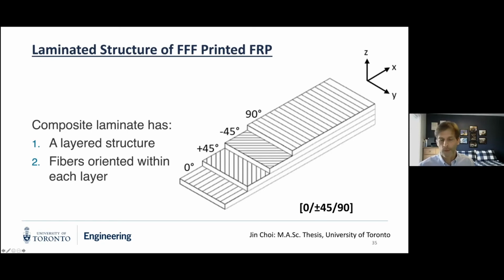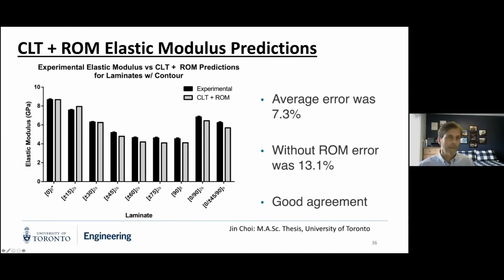And this is normal for composite manufacturing, even conventional manufacturing. And this is some of my material science research, so we've investigated the effect of how you build this layered structure up on the strength, and particularly the modulus. And when all the fibers are pointing in one direction, it's stiffer in that direction, but it tends to be brittle and can snap in the transverse direction. So for sure, in a sheet, you may want to lay down some layers at angles.